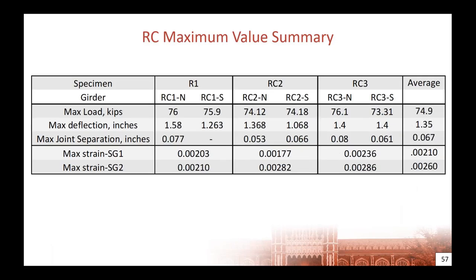For the retrofit construction specimen, however, we did see a slightly higher load, slightly lower deflection, slightly lower joint opening, and strains that indicated yielding of our negative moment steel. So we had a slightly stiffer connection.